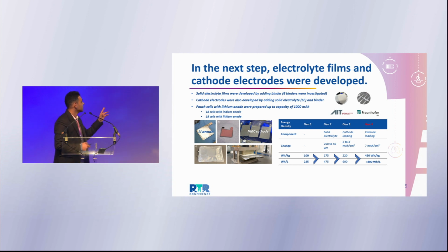And here you can see the initial cells with indium anodes. We made these cells. And the first generation of these cells had the energy density of 100 watt-hour per kilogram and 225 watt-hour per liter.